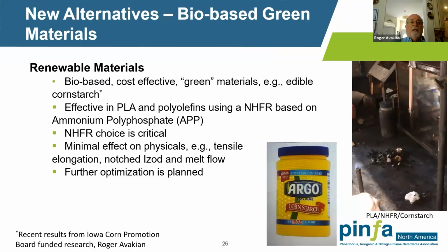I did work in both PLA and in polyolefins, as I mentioned, using ammonium polyphosphate. The choice of the non-halogen flame retardant is critical, particularly with regard to color generation. But we were able to achieve a UL 94 V0 in the PLA and some other polymers as well, with minimal effects on the properties. For instance, tensile elongation, notched Izod, and melt flow.